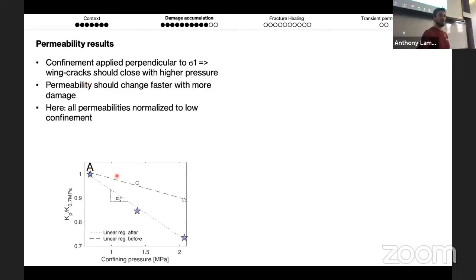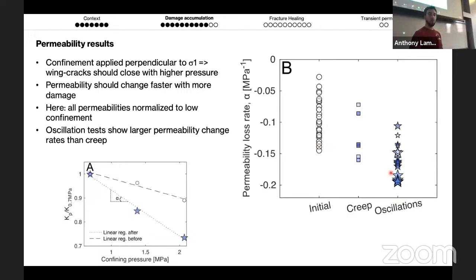So what I did is, as I said, measured the permeability before and the permeability after, and then take the slope of these changes. I've normalized to the low confinement pressure just to get rid of the effect of the sample variability, pretty much. But that's always normalized to the sample's low confinement counterpart. So when we look at this, what we see is that the permeability change rate is actually becoming more negative, or that's a negative slope. So the more negative that value is, the more rapidly it changes. And again, that permeability plot shows me that the oscillation test will produce more damage than the creep test. So some of this elastic energy in the oscillation test is actually transferred into the sample and creates inelastic damage. So elastic waves create inelastic deformation.